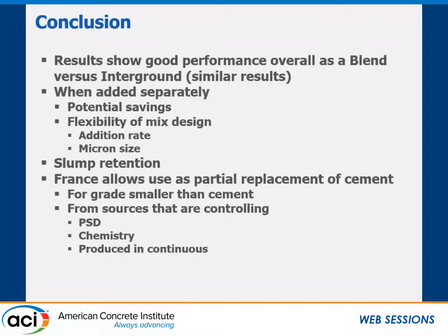As a conclusion, we can see that whether limestone is interground by the producer or blended separately, performance in regular concrete is very similar — and we already had very good results in SCC. Can we go to higher replacement dosages? It depends on the mix design and how much excess cement you're using due to poor aggregate gradation. In certain cases you could use more, but with a good gradation and already-minimum cement content, you likely can't replace more than 15%.